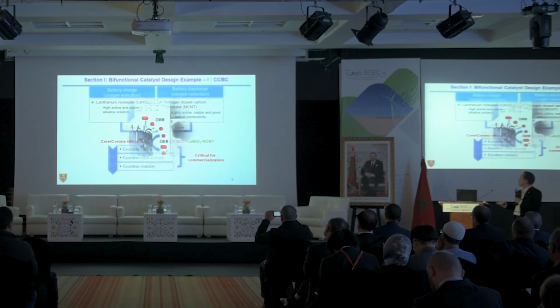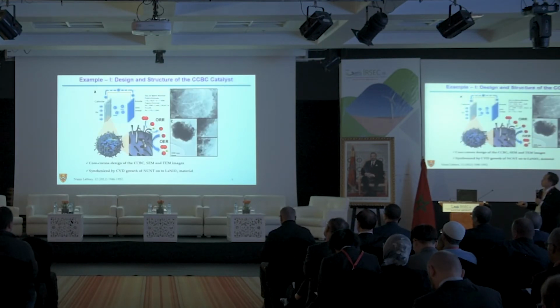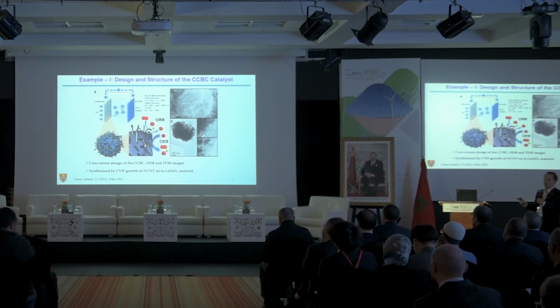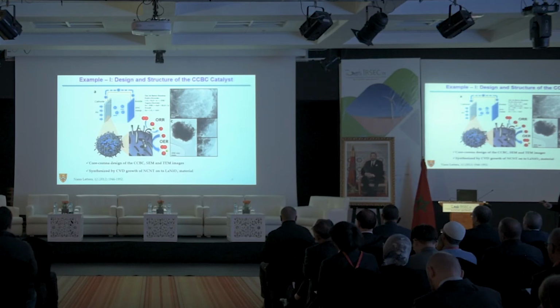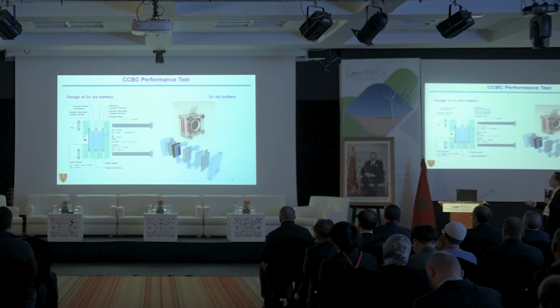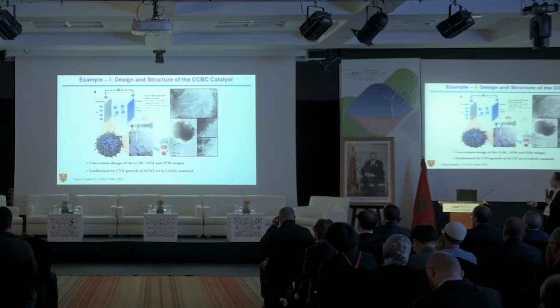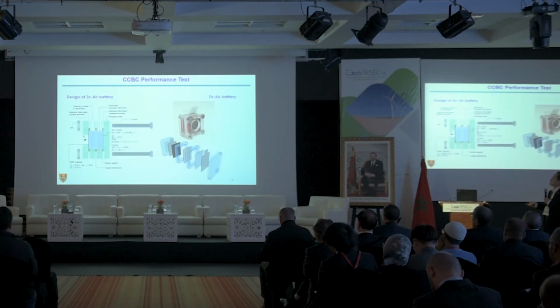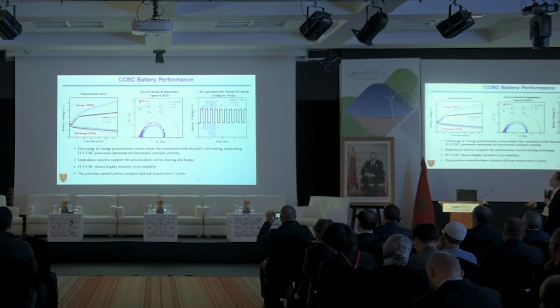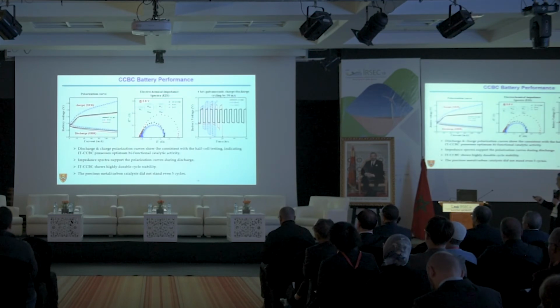So the way we do is we try to have the lanthanum nickel oxide nanoparticle first. Then on the surface, we grow by the CVD methodology the nitrogen-doped carbon nanotube on the surface of this particle. And here we call this a corona structure catalyst. So at that time, we successfully synthesized this kind of catalyst, and we made a homemade zinc battery at that time because there was no standard cell available at that stage.